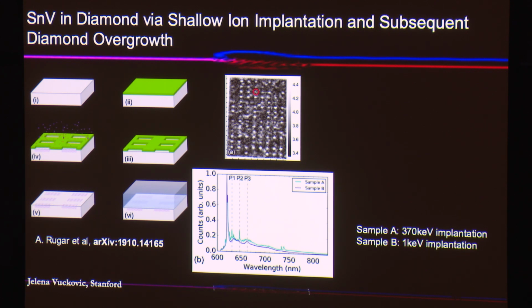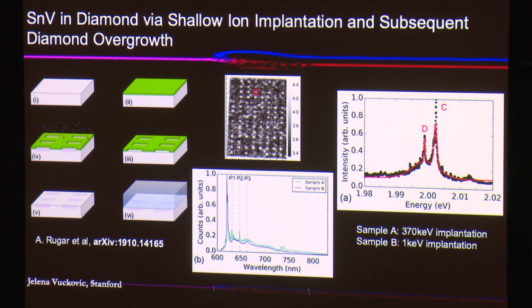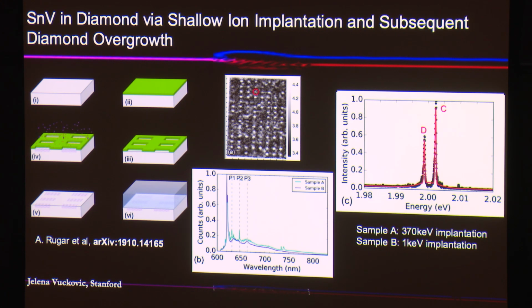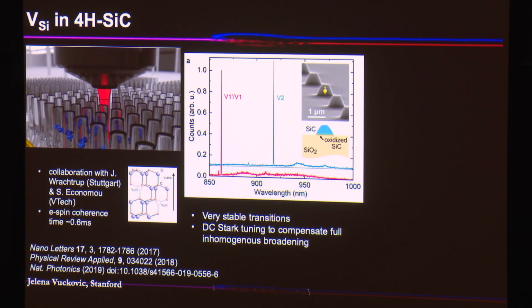As a result of this process, a lot of lines that people, including us, couldn't really explain in early papers, that were attributed to some other color centers or their different states, were basically eliminated, because it turned out that they were just coming from the process that was not optimized for growth. And also line widths of transitions are much narrower. So now, having these developed, we're using this shallow implantation process combined with fabrication to make devices. And we think that this is much more advantageous than just bombarding with very energetic ions and hoping that things work out.